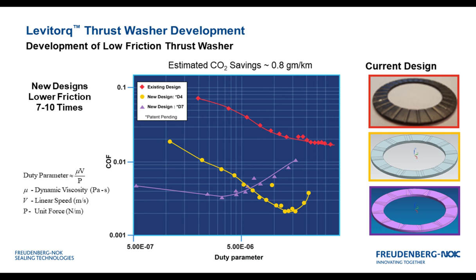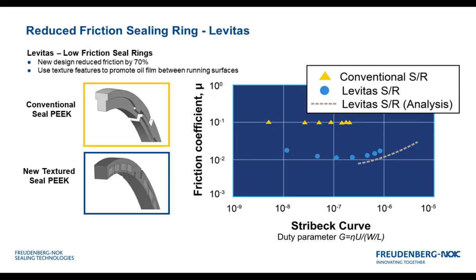And that is critical to really getting to these ultra-low frictions. The estimated CO2 savings on one of these parts was 0.8 grams per kilometer based on the calculations we used. You can see it can be pretty significant depending on the application and the conditions of use.